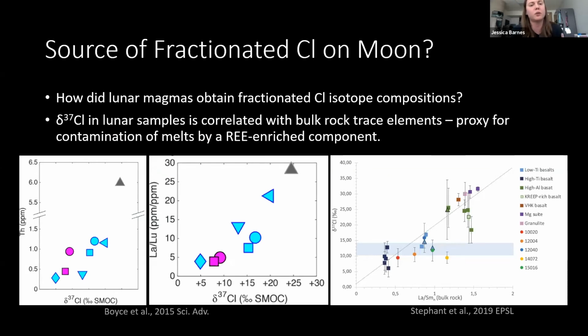And so what's the source of this fractionated chlorine on the moon, and how did magmas obtain those compositions? Well, a study that came out just before ours in 2015, and Alice's work and our work, we all realized that we were studying a range of sample types, lunar basalts that have varying amounts of KREEP component, that residual lunar magma ocean component, and crustal rocks. And so we all decided that there's a good proxy for KREEP component if we look at the trace elements. So by comparing the chlorine isotope compositions, and just to confuse everyone, chlorine isotopes are now on the x-axis for the Boyce data, and they're still on the y-axis for the Stephant data. But you can see that if we use, for example, thorium or lanthanum-lutetium ratios, or we use lanthanum over samarium, that we see a correlation between trace elements, rare earth elements, and also chlorine isotope compositions.